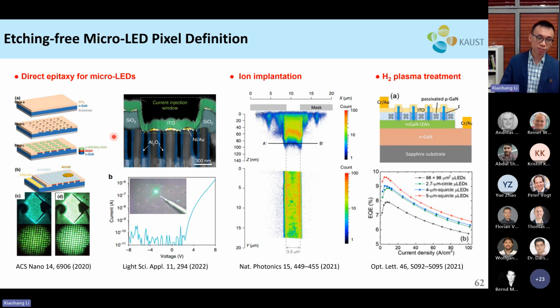For example, people utilize direct bottom-up epitaxy to get micro LEDs, and then people have utilized ion implantation to isolate the areas of micro LED. But you can still see that there are different ions inside the LED mesa as well. And also, people have tried to utilize hydrogen plasma passivation to passivate the P-type gallium nitride, so that you can form the mesa. You can form the pixel.